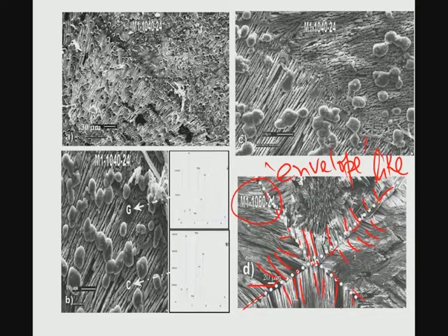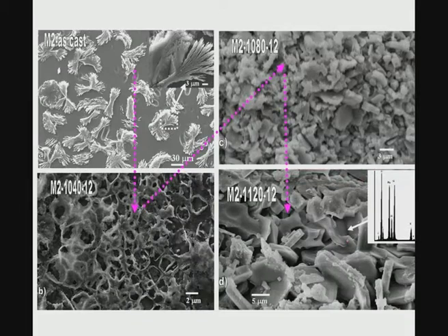So, this kind of morphology is indeed different from what I described in earlier slides, where I showed cabbage-shaped crystalline morphology or star-shaped morphology. Compared to that, this is indeed different. The other interesting thing you notice here is that the stacking of this crystalline, rod-shaped morphology is very dense. It is not dispersed in the microstructure the way you have seen before, but a very dense straw-like morphology, and this kind of dense arrangement of crystals in the glass matrix would give rise to better mechanical properties, which we will see in some of the next slides.